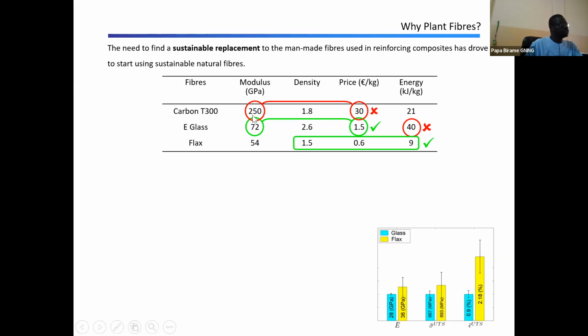If we look at the Young's modulus, we can see that carbon T300 has a high modulus compared to glass and compared to flax, which among the three has the smallest modulus. But this modulus must be related to the density. When we look at these three materials, we see that E-glass, which is the most used material, is the heaviest, and flax, which had the smallest modulus, has the smallest density. So the mechanical properties are to be divided by the density to get the specific value. And when we do that exercise, we see that the plant fiber, flax, starts being competitive.